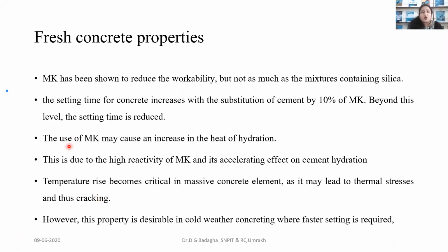Okay, so the use of metakaolin may cause an increase in the heat of hydration. This is due to the high reactivity of metakaolin and its accelerating effect on cement hydration. However, this property is desirable in cold weather concreting, no doubt. From the PPT and discussion, you can see that some negative things are there.